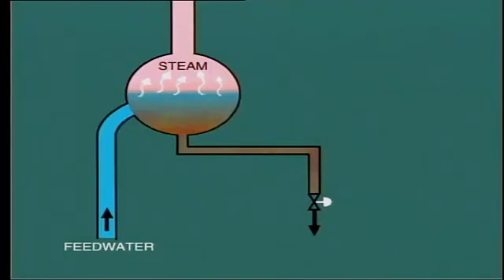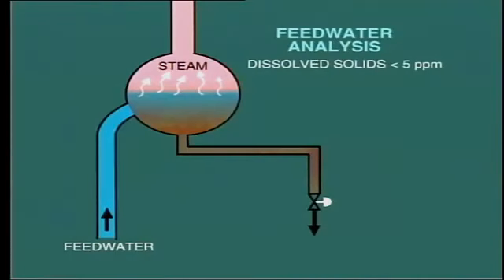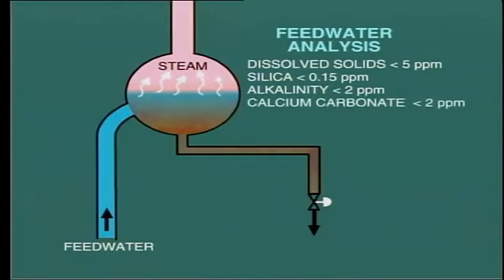The actual limits established for boiler feed water contaminants depend upon the particular boiler operating pressure and temperature and operating regime. However, we would typically expect to find the following analysis of boiler feed water and makeup. These concentrations are given in parts per million, ppm. Total dissolved solids are less than 5 ppm. Silica is below 0.15 ppm. Alkalinity is 2 ppm or less. Hardness as calcium carbonate is at 2 ppm or less.